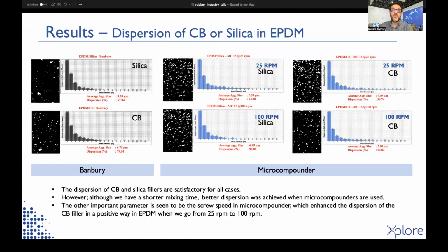It was observed for EPDM silica compounds that the dispersion of silica in EPDM was much better in the compounds prepared with the microcompounder compared to the Banbury mixer. Moreover, the average particle size of silica decreased significantly from 10 microns to 5 microns. The dispersion quality percentage of silica was much better in the composites prepared in the microcompounder. Similar test results were also obtained for EPDM carbon black composites.